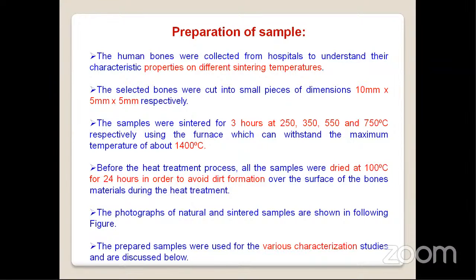Okay, so here I have selected the bone materials, that is, proper bone materials without any impurity, and cut into small pieces of dimensions 10 mm, 5 mm, 5 mm. That is length, breadth, and thickness. Okay, this is in the millimeter range only. Now after selecting these bone pieces, we are going for sintering for 3 hours at 250 degrees centigrade, 350, 550 and 750 degrees centigrade in the furnace.